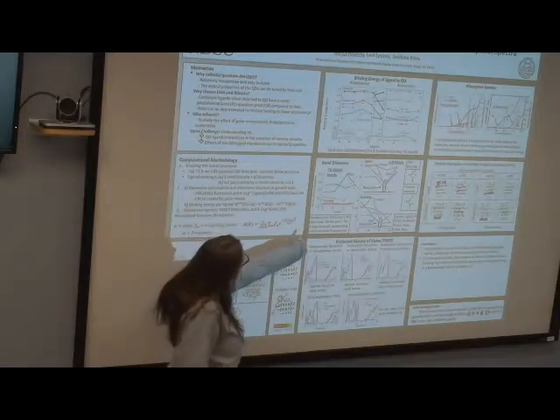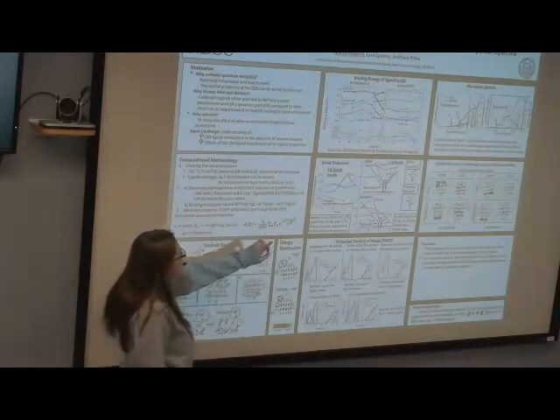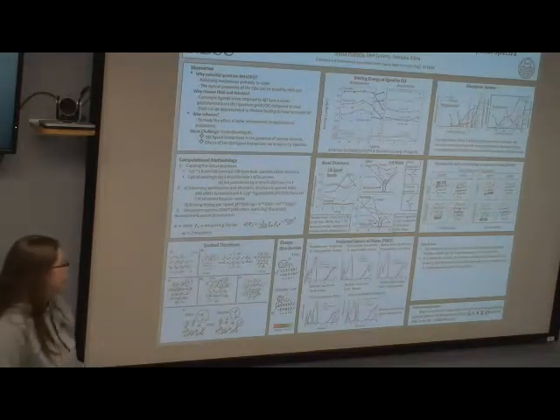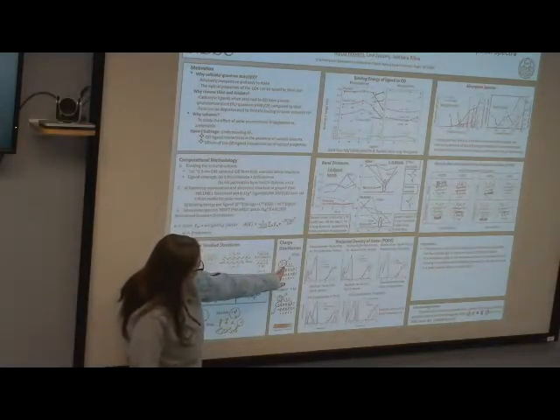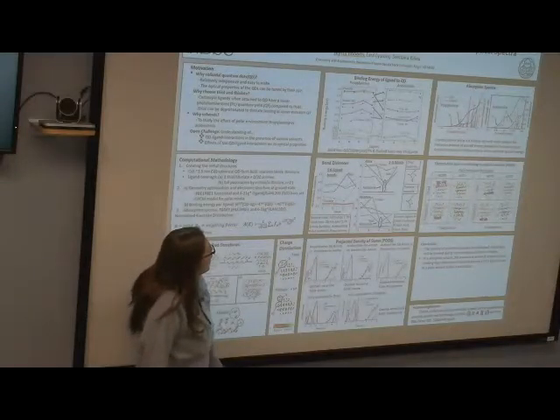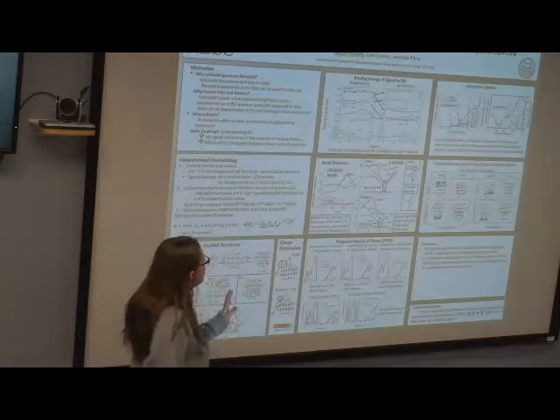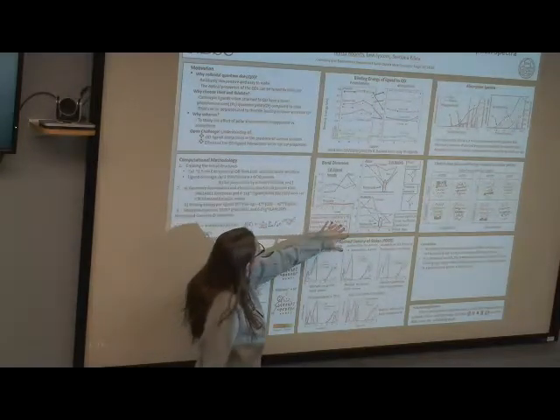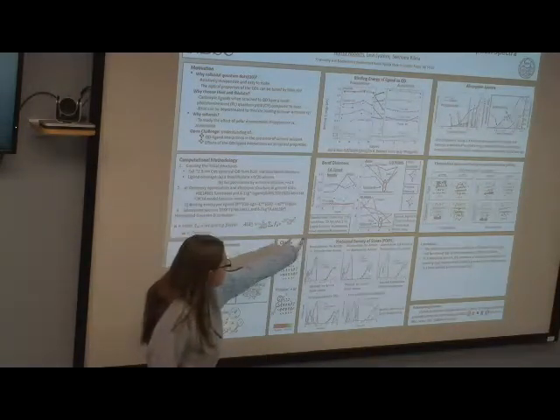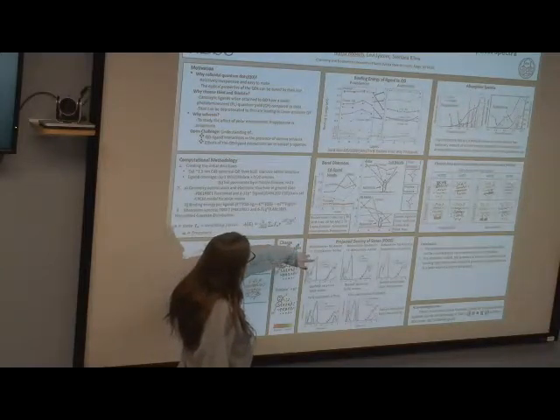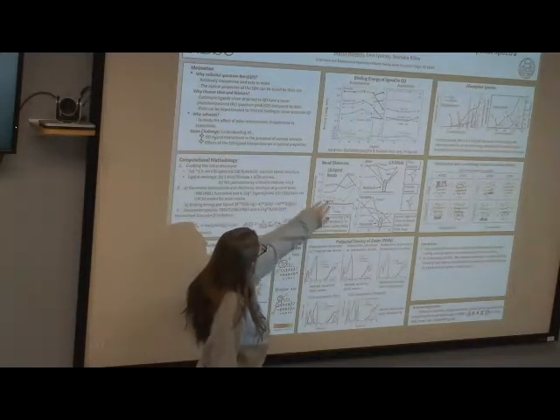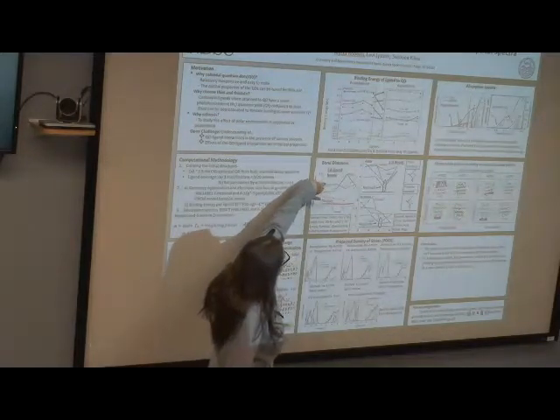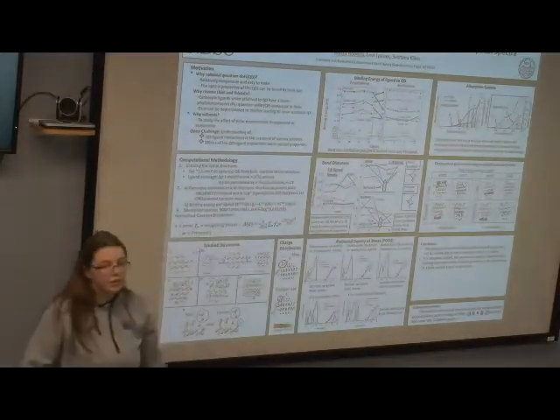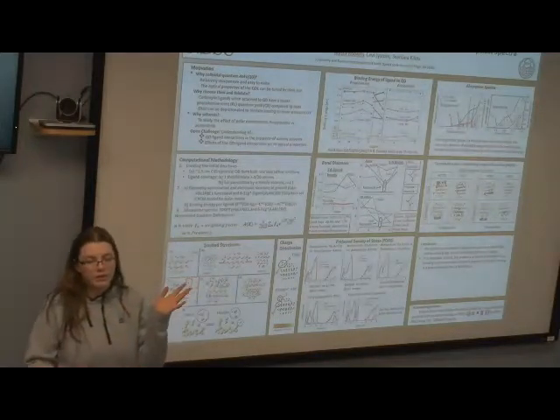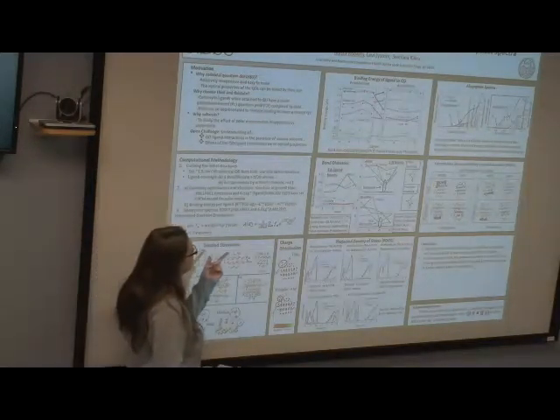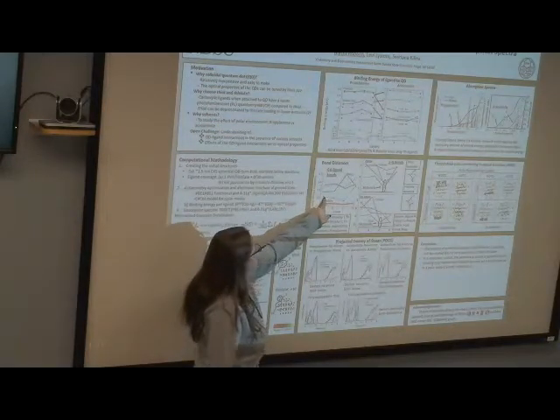And then here we can see the bond distances. So this is specifically between the cadmium and the sulfur of the ligand. You can't see the cadmium, it's underneath here, and the sulfur. So it's pretty much, thiolate is fairly unaffected by the change in solvent because the empty symbols are acetonitrile and the filled symbols are propylamine. So these two here, it's hard to see on here, but these two are the acetonitrile, and they're relatively speaking a longer bond distance than propylamine, which are here and here.